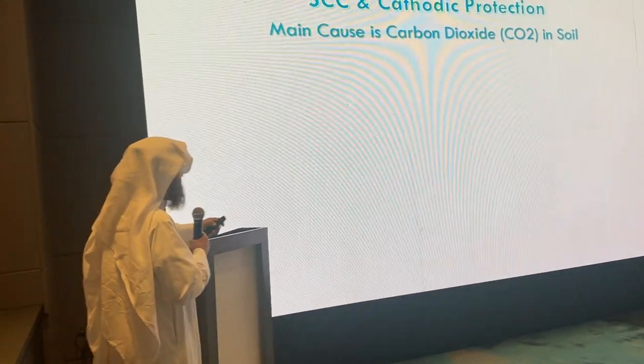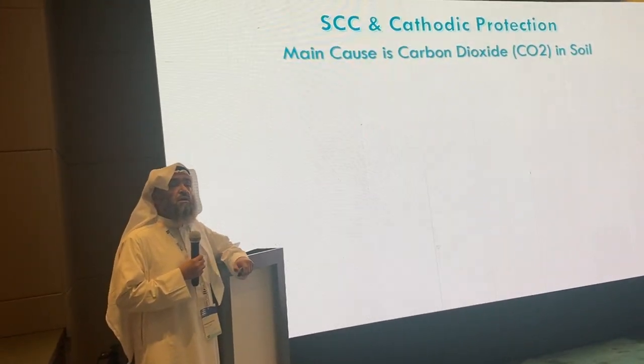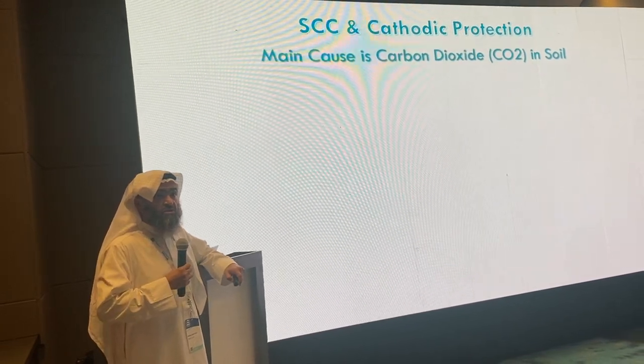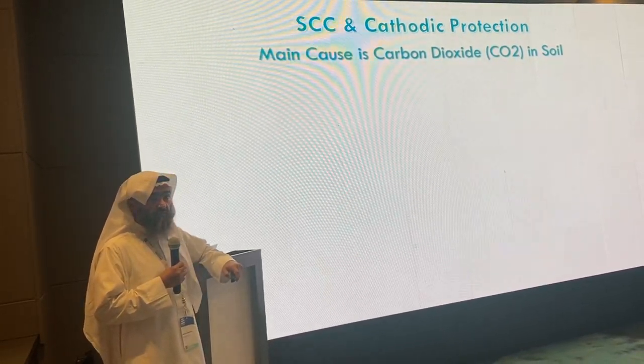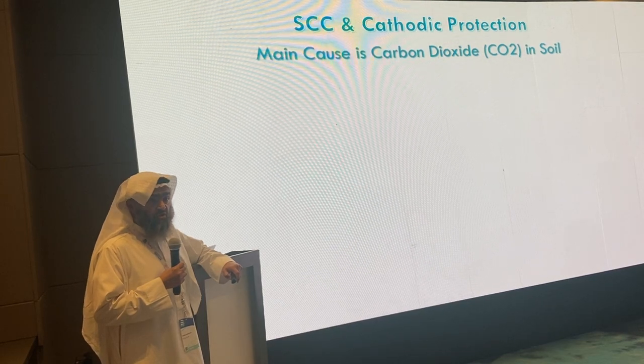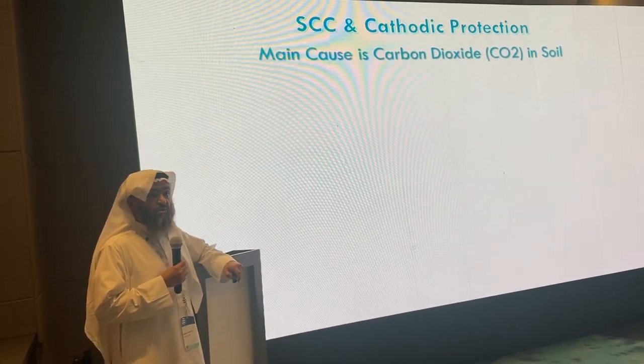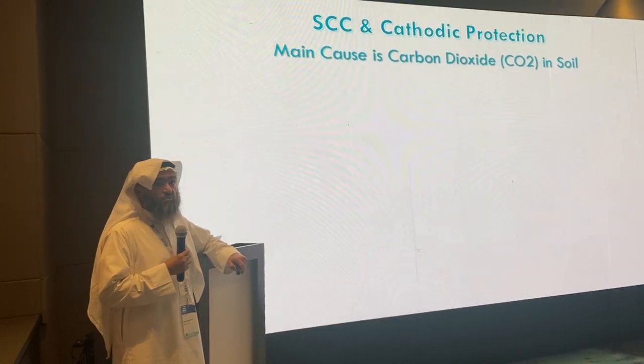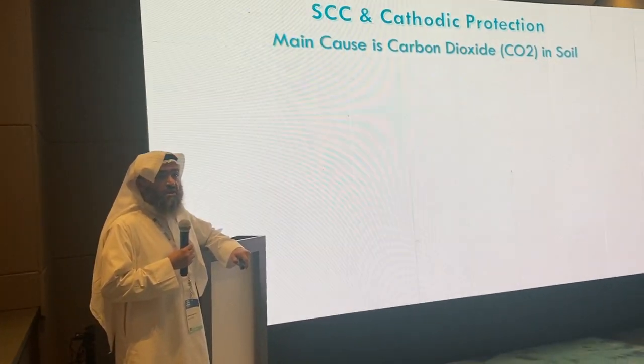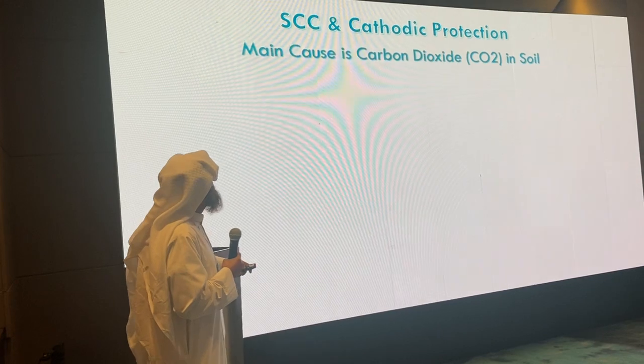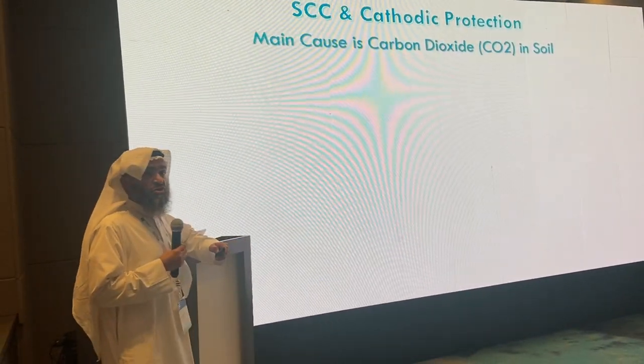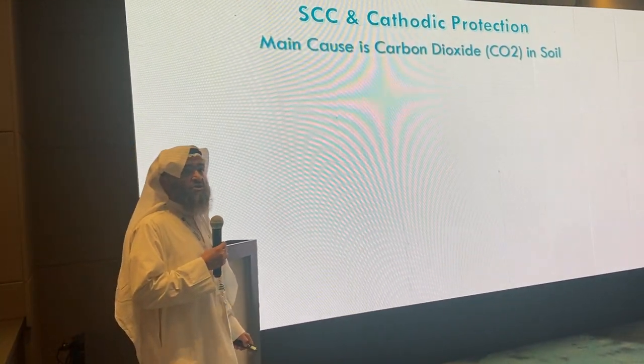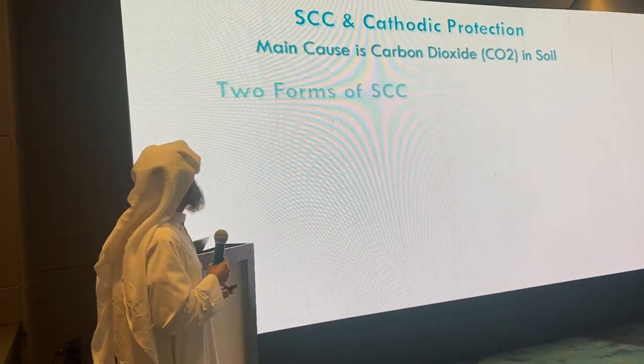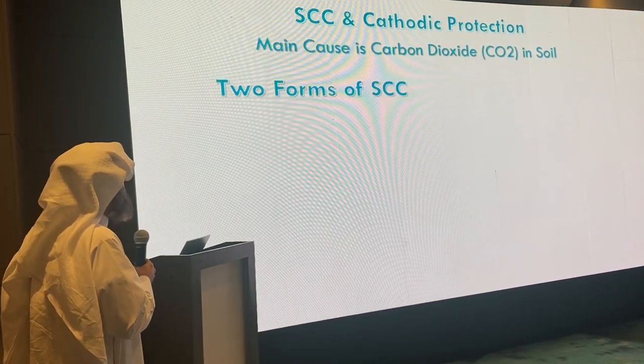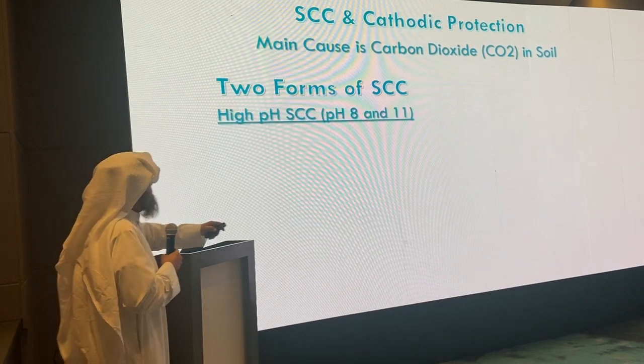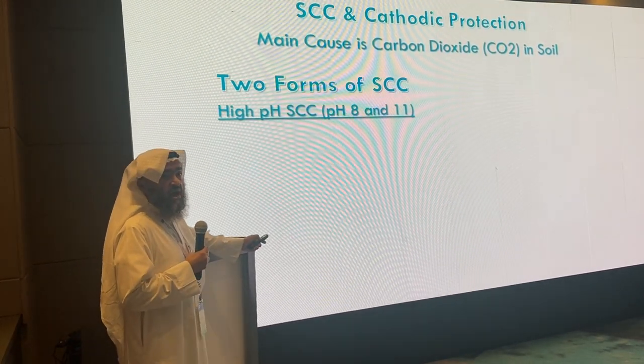As I said, stress corrosion cracking is the most important corrosion cause that makes pipe fail, mainly because it is catastrophic and unpredictable. So you might have a failure in your pipe system 2 or 3 years after starting the operation. The main cause of stress corrosion cracking is the availability of CO2 in your soil. There are 2 types of stress corrosion cracking. High pH stress corrosion cracking, where the pH is above 8.